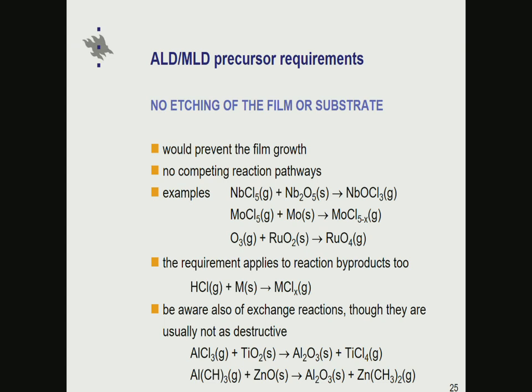And if these reactions occur, like here, this is one of our first observations: niobium chloride, when pulsed over niobium oxide, can form niobium oxide trichloride, which is a volatile compound. Actually, this reaction is so complete that one can completely etch away niobium oxide using niobium pentachloride. But if trying to deposit films with niobium chloride and water, one has very irreproducible results. The same applies, for example, to molybdenum chloride with molybdenum metal, and ozone with ruthenium dioxide producing ruthenium tetroxide.